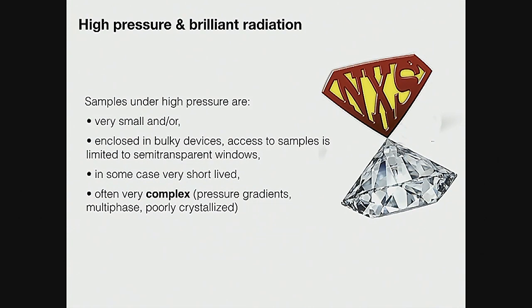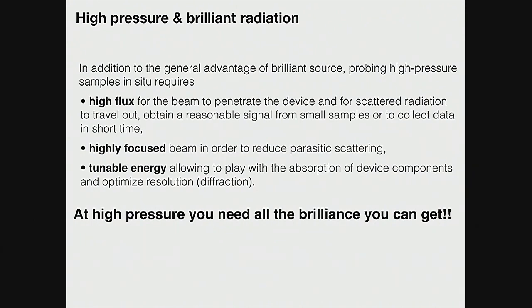So you have a very small sample, or a sample in a bulk device, and you can see that sample only through narrow semi-transparent windows, and the sample might be very short-lived. Samples can also be, or in general they tend to be, extremely complex, because if you picture things, you're smashing something, it's not going to be your ideal beautiful sample. And if you start heating with different techniques, you start immediately having high and low pressure phases, part of the sample reacted and unreacted. So of course you want high flux just to be able to collect a decent signal from a small sample, or to collect a signal in a short time of a shock compression.